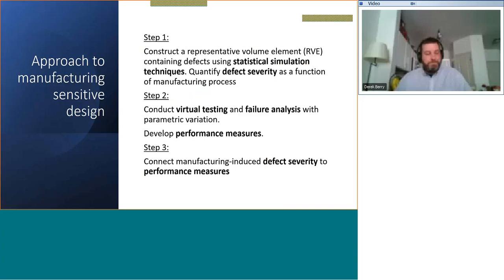So how do we approach a manufacturing sensitive design? That is a design that, already at the stage of dimensioning of the composite structure, takes into account what type of internal structure we are going to get, what the defects are, and how we characterize those. I have developed a three-step process in this design. The first is where you take some observations, and today we can make observations in many different ways, not just optical microscopes but X-ray tomography, digitize those observations, and from there create, through statistical simulation techniques, something called a representative volume element. This is a representation, in a statistical sense, of what is in the interior of a composite, and then quantify that with defect severity measures that I've been developing in the past few years.